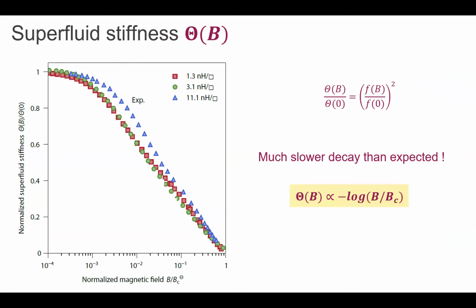Now it's different from molybdenum germanium because it's not a log-log plot, it's a semi-log plot. And what we obtain is a logarithmic suppression of the superfluid density. What does it mean? It means that the superfluid density is much more robust in this vortex glass than in the standard elastic lattice system. And if you want to see what we should expect for a collective pinning, if you put a power law, you would expect this. So you see that at this distance to the critical field, your vortex glass is super robust, super stiff actually.